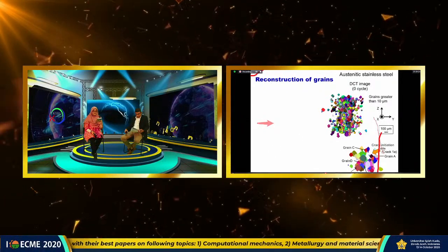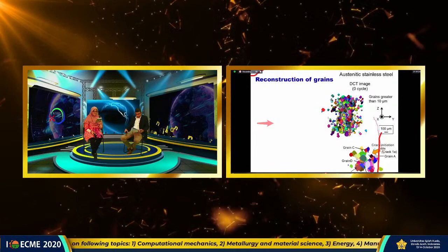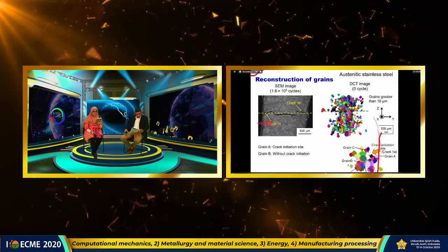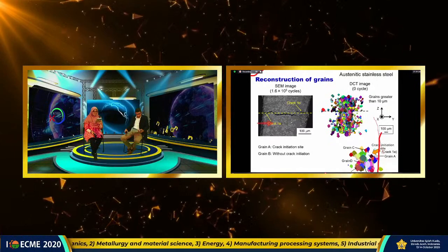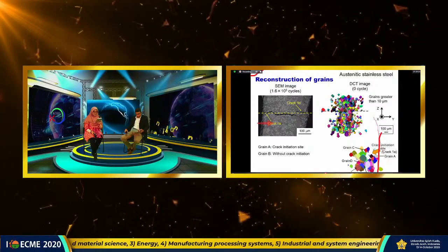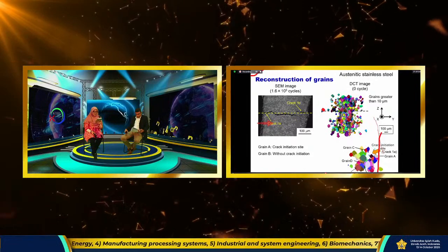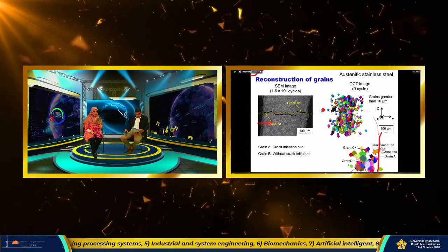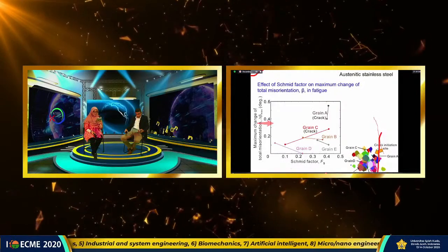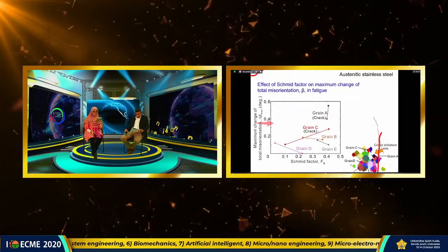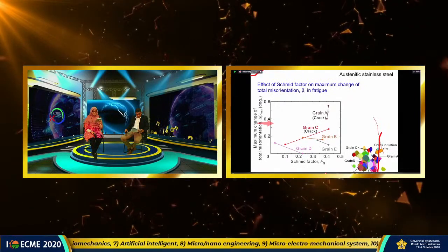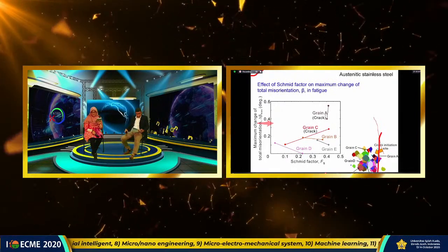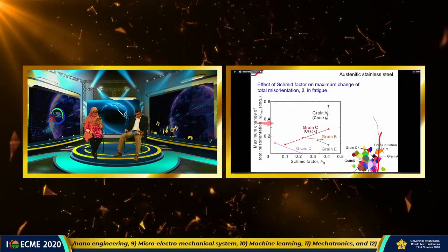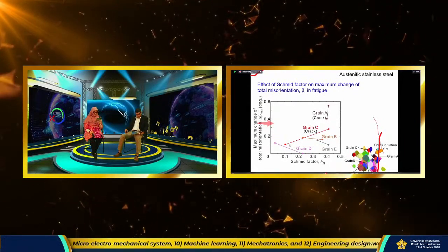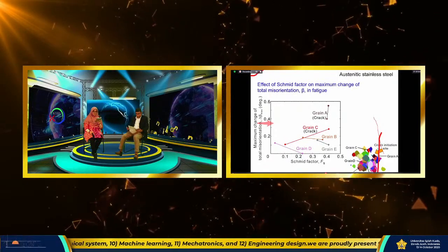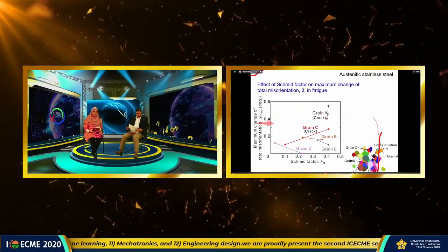You can see grains. We have a crack like this. This figure shows a cross section. We have a crack initiated here, and it's a change of misorientation of cracks. Each one is a grain. We have a large change of misorientation like this. Others, the change is very little. So cracks initiated from this grain.